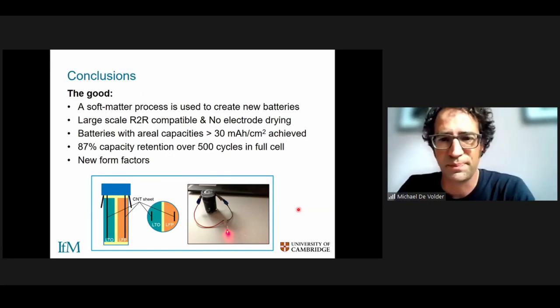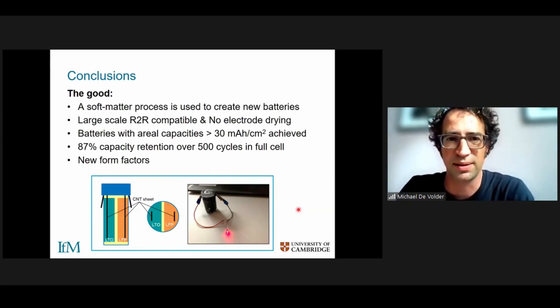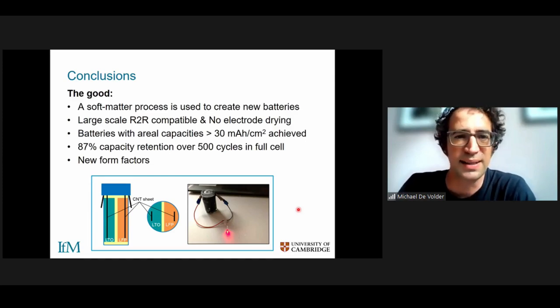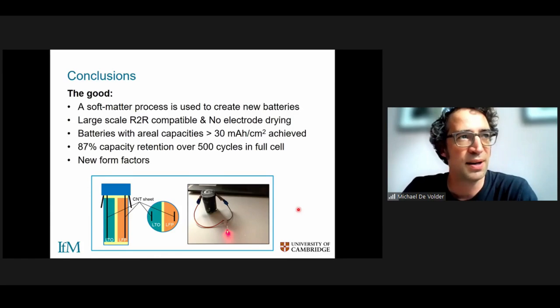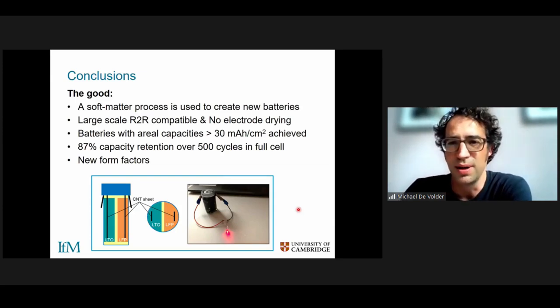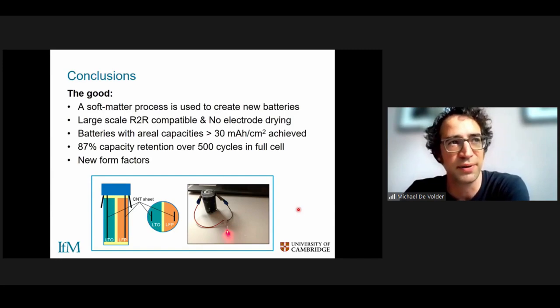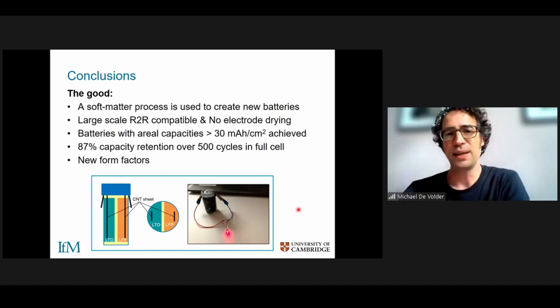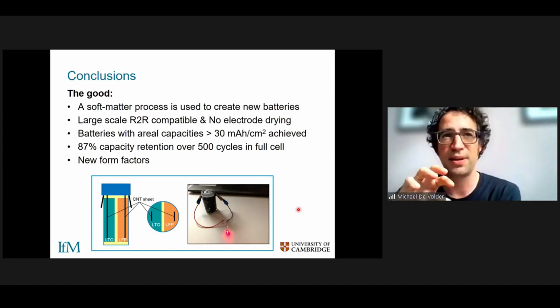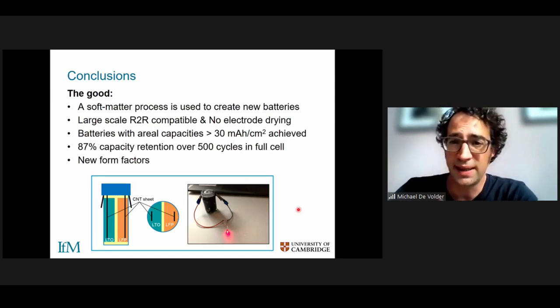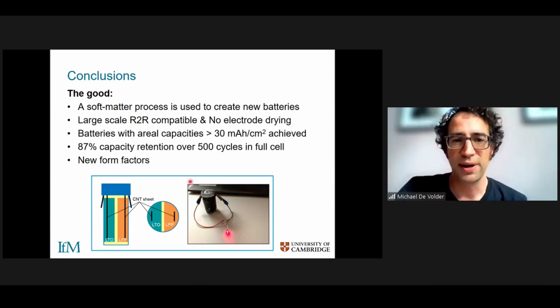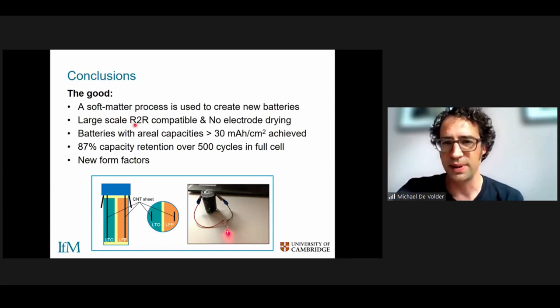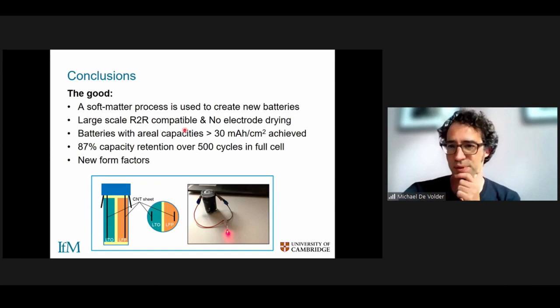So that brings me to some conclusions I want to draw based on this process. First of all, I think this is a fairly nice example of how a polymer phase segregation process, or soft matter process essentially, can be used to shape the internal structure of a lithium-ion battery electrode, and in particular by creating a bicontinuous material structure. These processes allow for making very thick electrodes with still good battery performance, which is quite unique. We also have been able to show that it's compatible with a continuous roll-to-roll coating process.